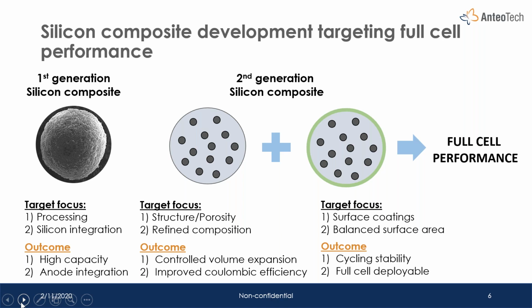And so this expansion needs to be managed, including the flow-on effects, which are excessive SEI layer formation and electrolyte degradation on the surface of these materials. To resolve this challenge, initially we resorted to nanosilicon, and nanosilicon needs to be integrated into the anode in sophisticated ways because it is a very small particle, has a high surface area and low density. And this is exactly what we're aiming to achieve with our first generation of silicon composite material, where we looked at processing of nanosilicon into these larger structures and the integration of silicon into the anode coating, but also to demonstrate that we can deliver very high capacities with these materials.